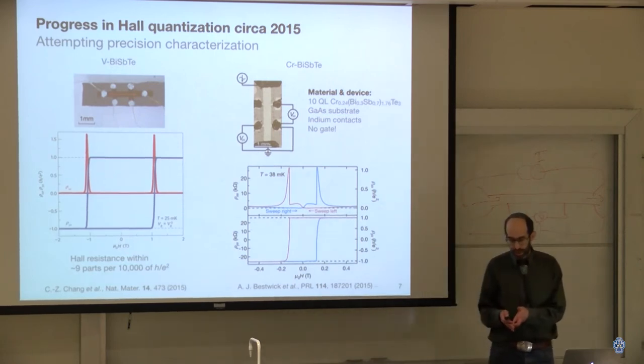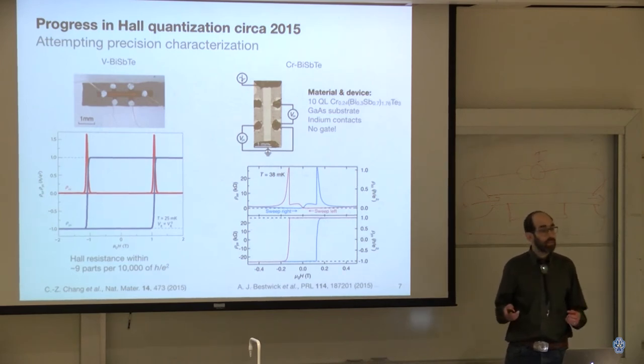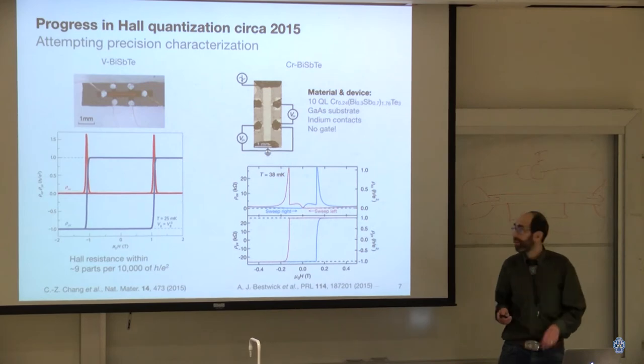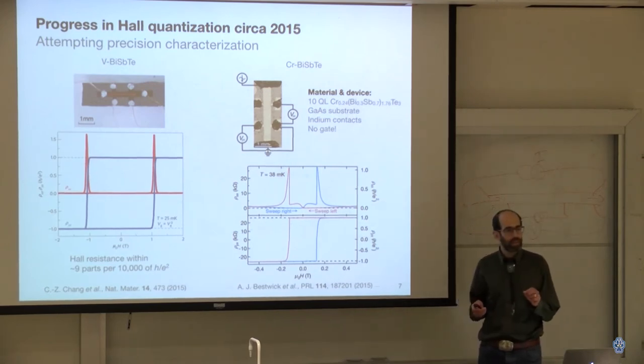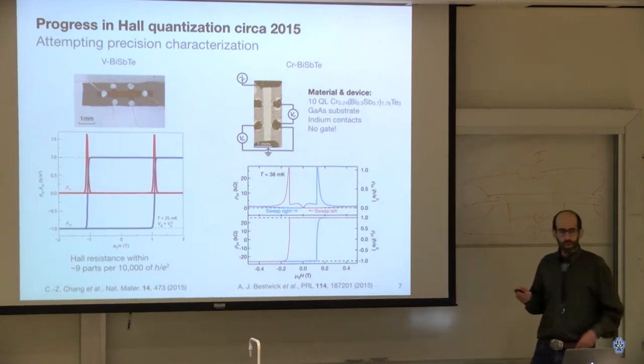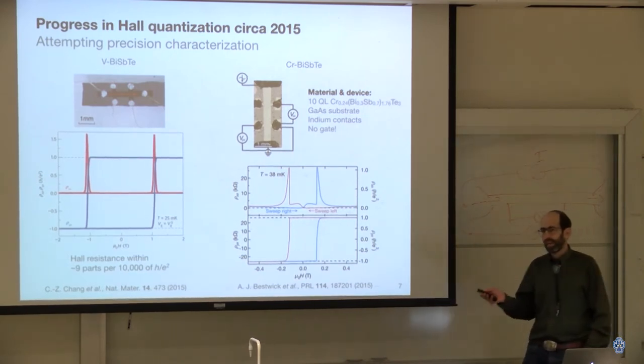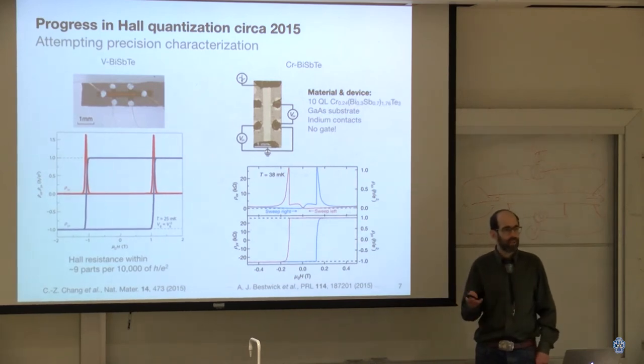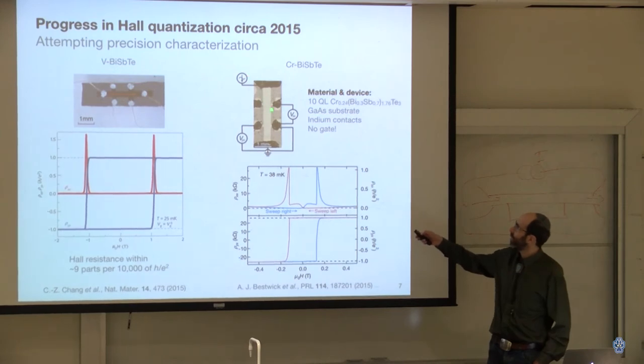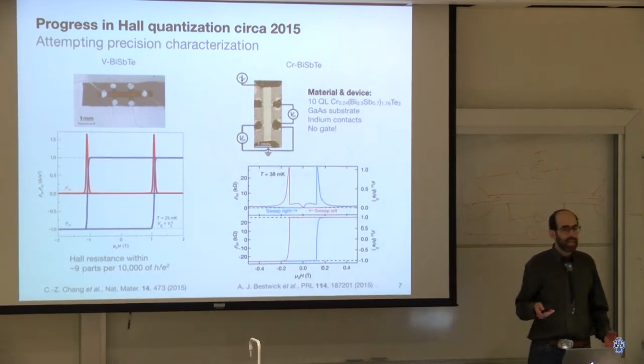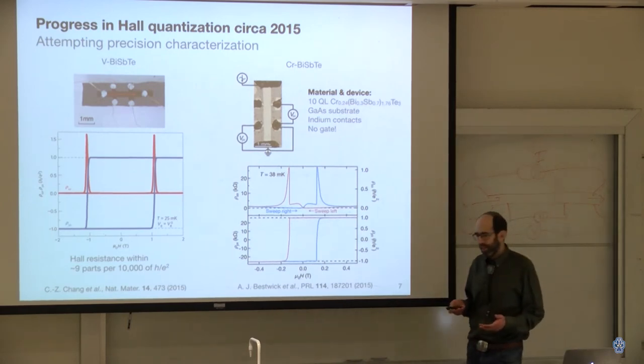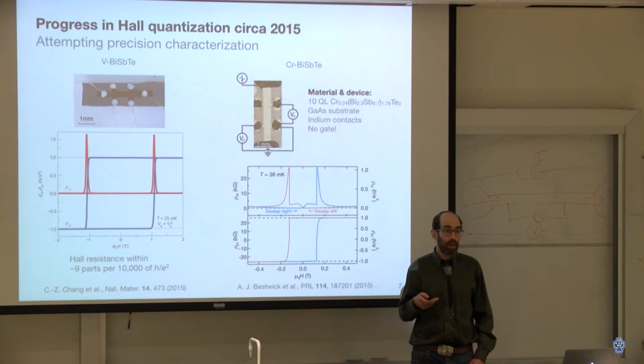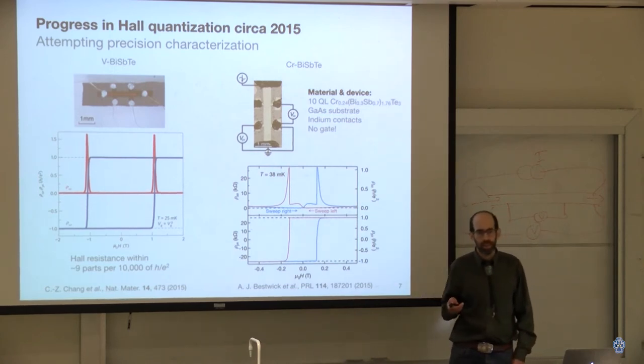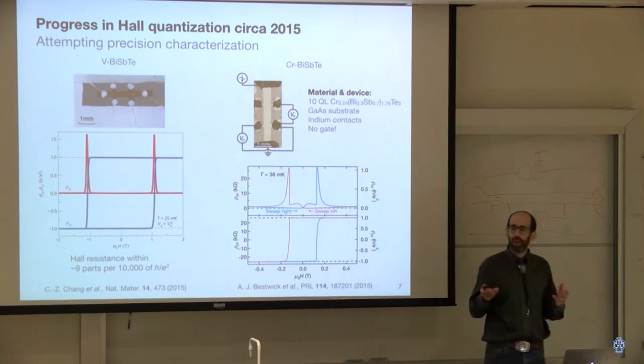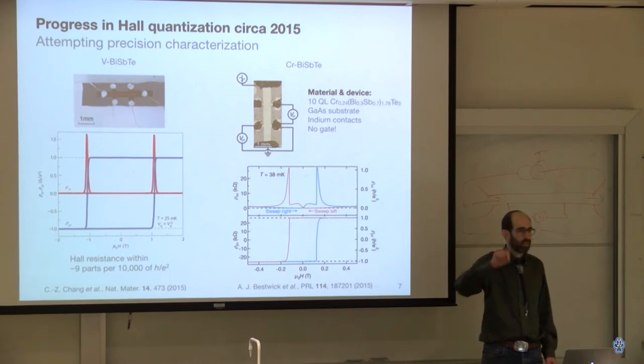So we are used to using lithography in my group, and in fact, not even with light most of the time, but with a beam of electrons writing like a pencil, which can get very fine, down to about 10 nanometers, tens of atoms across. So we were doing lithography on these samples, and we found that all of them had too many electrons in them. They didn't have the right properties. They weren't insulating in the bulk of the material. And so I had to have a little bit of humility and say, I've been going around talking about the pioneers in this field, who were at Tsinghua University in Beijing in China, and saying that the way they made their samples was by cutting-edge lithography. That is, by taking a very sharp diamond tip and scratching things.